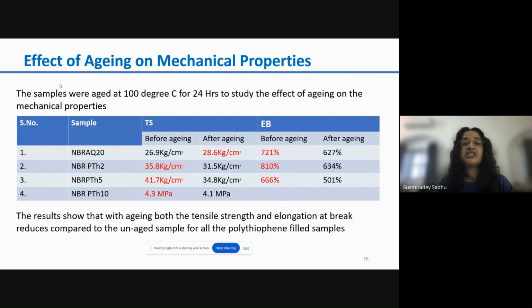We have also aged the sample at 100 degrees centigrade for 24 hours to see the effect of aging on the samples. So it shows that with increasing loading of polythiophene from 2 phr to 10 phr, the effect of aging is much harsher on the samples, both on the tensile strength and elongation at break. And this is quite expected because polythiophene is a conducting material, so it will also conduct the heat better with an increasing amount of loading.